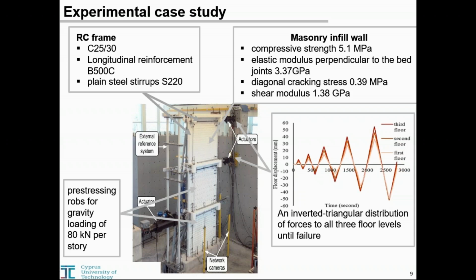Diagonal compression tests were performed in order to define the compressive strength, the modulus of elasticity perpendicular to the bed joint, and the cracking strength, as you can see in this figure. The compressive strength of masonry was 5.1 megapascal, and the modulus of elasticity of masonry perpendicular to the bed joint was 3.37 gigapascal. You can see the general view of the test setup.